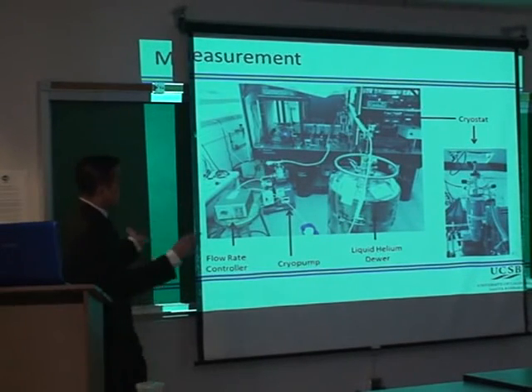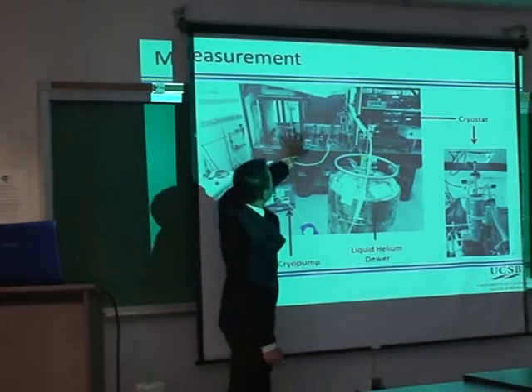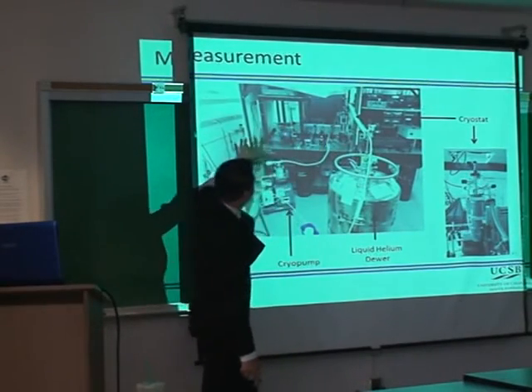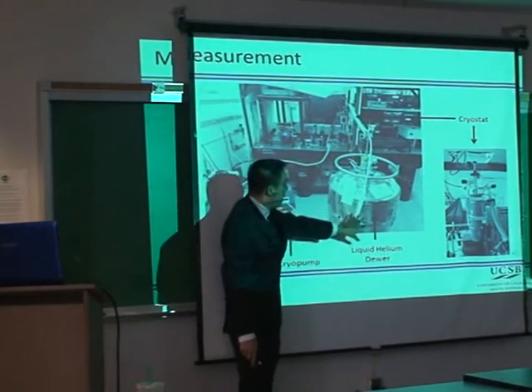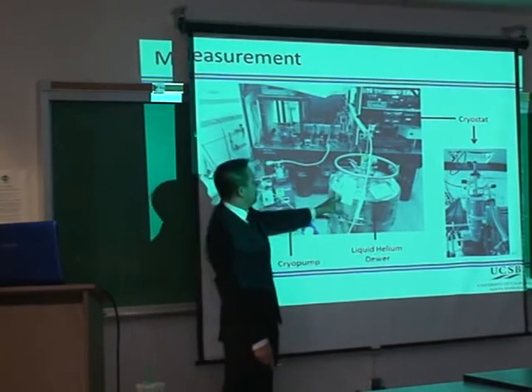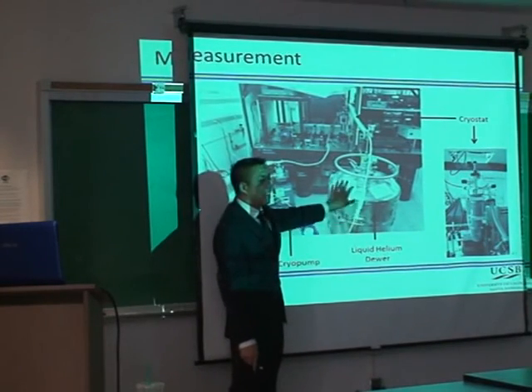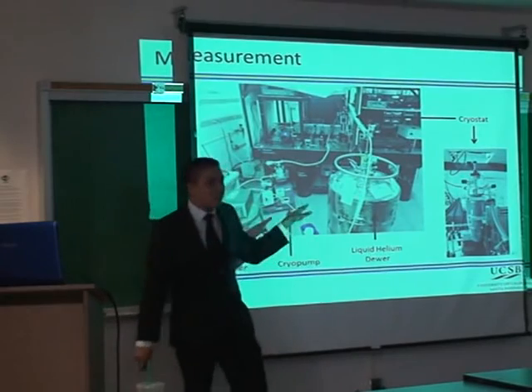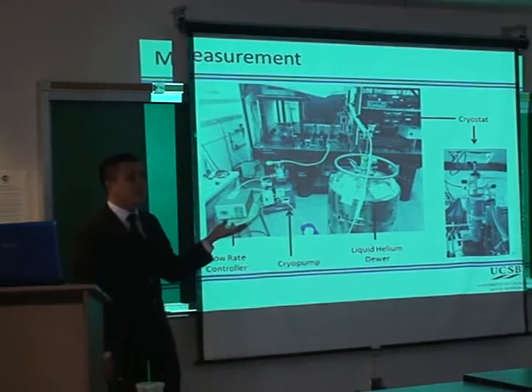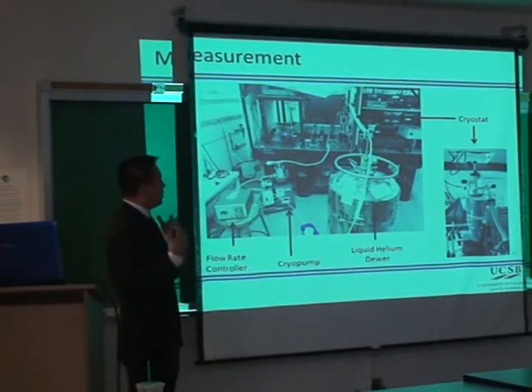And just to give you an idea of the setup, we had the laser set up back here, and we had to actually order this helium tank. And this is actually quite expensive. This was about $560 for this tank. And the problem with this is that not only is it expensive, but it kind of evaporates. And when you get this, you have to do the experiment right away.